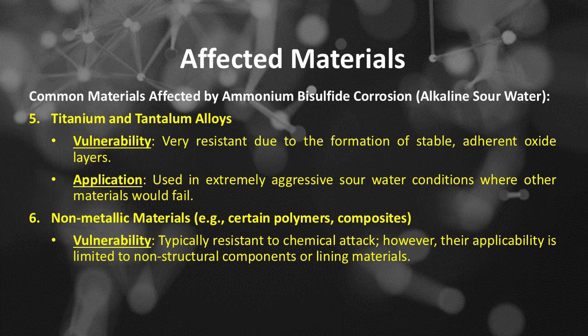Common materials affected by ammonium bisulfide corrosion or alkaline sour water, number 5, is titanium and tantalum alloys. The vulnerability of titanium and tantalum alloys: very resistant due to the formation of stable, adherent oxide layers. The application: used in extremely aggressive sour water conditions where other materials would fail.